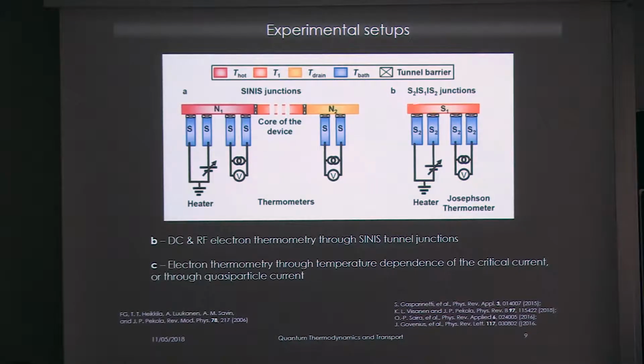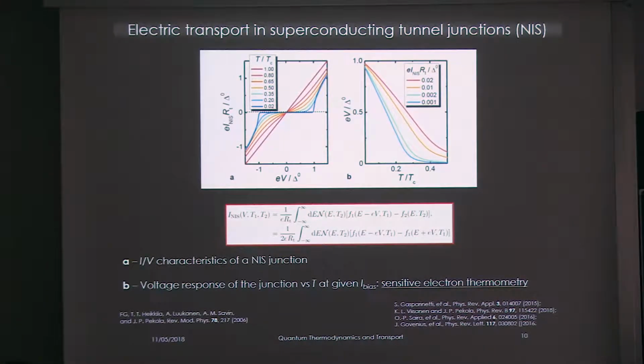In the case where we want to probe the temperature of a superconductor, we can deal with it in a similar way. We use another superconductor, typically with similar or different gaps, still tunnel coupled. And from the electric characteristic of this kind of object, we can extract a direct response and information on the electronic temperature established in these reservoirs. So I'm just giving some very basic concepts of how electric transport works, so that we can understand how we do thermometry.